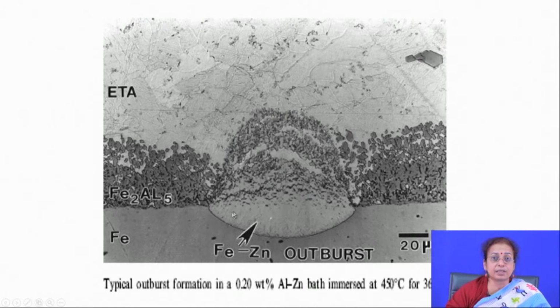That iron zinc intermetallic creates trouble because it applies pressure, as a result of which, after a while, there is breakage of the Fe2Al5 layer, which is called outburst formation. Outburst formation is never desired, because not only does it break the Fe2Al5 layer, but it can also apply such a high pressure that your coating can fall out.